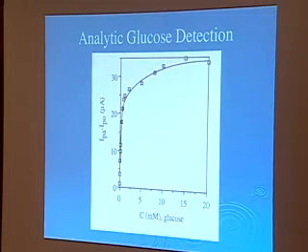We stop along the way when we have this puzzle and say, well, we don't know how it works, but it sure makes a great sensor. So we have the cobalt hexamine in there because we decided that was the best cation to use for the highest sensitivity. We're just doing cyclic voltammograms. We have the glucose oxidase, 10 micromolar in the solution, and we plot the difference between the modified electrode peak current in the absence of the glucose and in the presence of the glucose. And you see we get a plot like this as we increase the glucose.